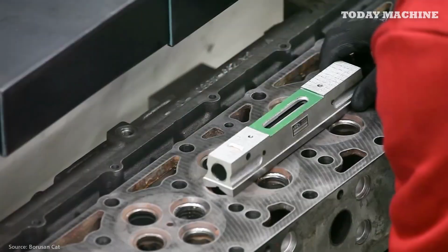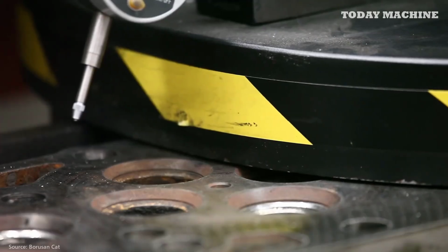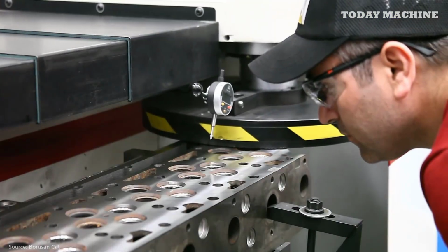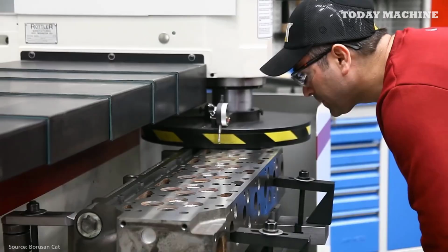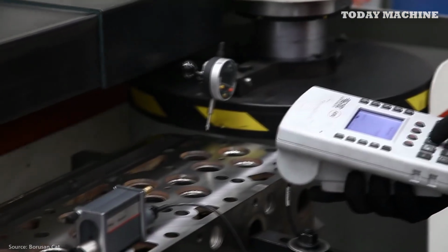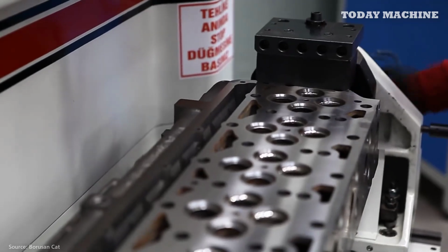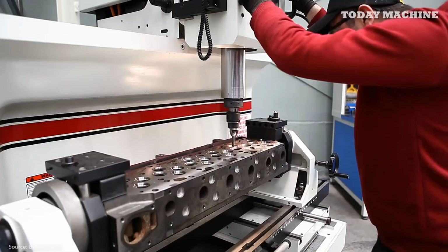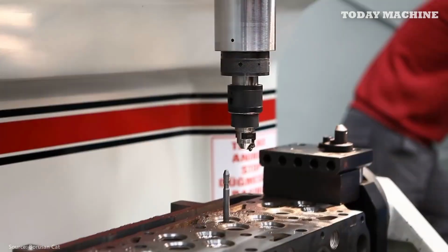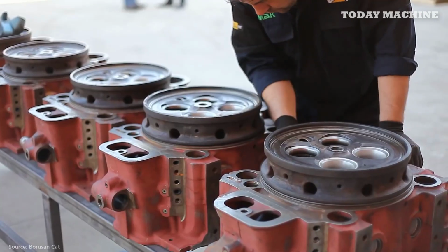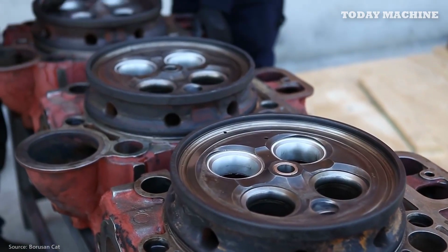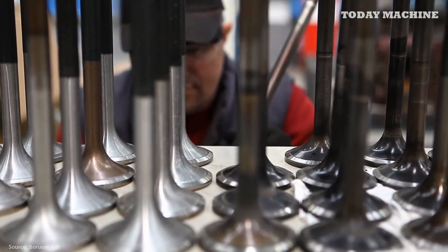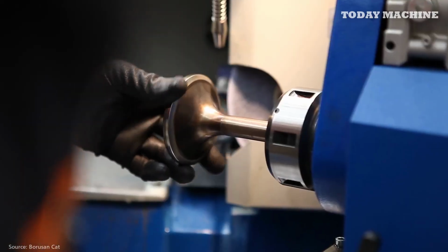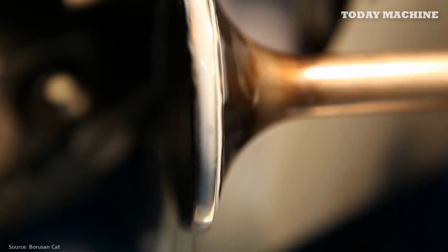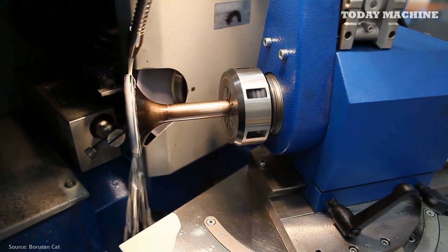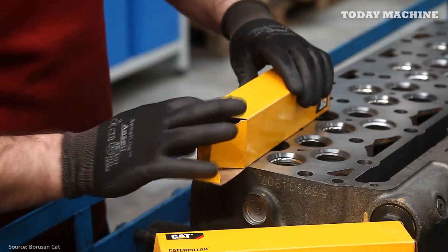Materials used for cylinder barrels include precision steel tubes with a typical hardness of 60 HRC and chrome-plated piston rods for corrosion resistance and durability. Surface roughness is controlled to Ra less than or equal to 0.2 micrometers to ensure smooth operation. In revision, repair and refurbishment processes involve disassembly, cleaning, inspection for wear or damage, honing the cylinder bore, replacing seals, and chrome plating the piston rods. Load and pressure tests up to 700 bars are conducted to ensure the cylinders meet OEM specifications before being returned to service.